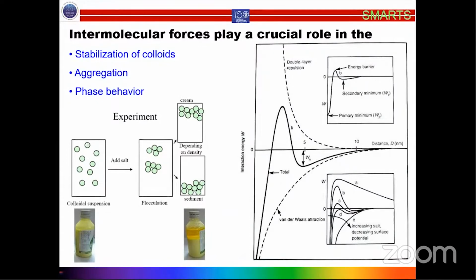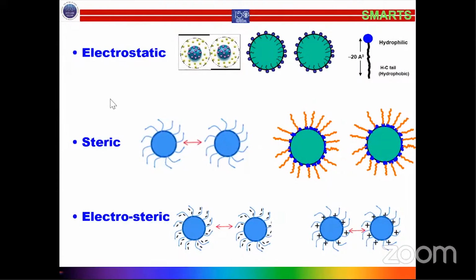So these are the different techniques that are used to stabilize the system. You can use electrostatic, steric or electrosteric stabilization by using surfactants or charges to stabilize these particles. In this case, you have steric interaction by uncharged or neutral polymers. You can also use diblock polymers like the one which is shown here, which will have a hydrophobic and a hydrophilic part, where one can anchor to the surface and the other can protrude into the solution. This is one way of stabilizing. And you can also use polyelectrolytes or neutral polymers with a surfactant, where you will have electrostatic interaction between them.